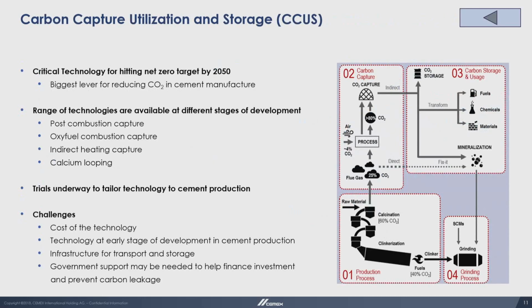If you look at a bit of detail on carbon capture, it's worth looking at the diagram on the right there, at the bottom, the box number 1. In terms of the amount of CO2 that's produced in cement manufacture, around 40% of it is associated with the heating up of the kiln and the raw materials that are used, but 60% is actually the chemical process, transforming the raw materials into cement. The chemical reaction releases CO2, and 60% of the CO2 is generated by that reaction. So what the industry is now looking at is how do we capture that CO2?